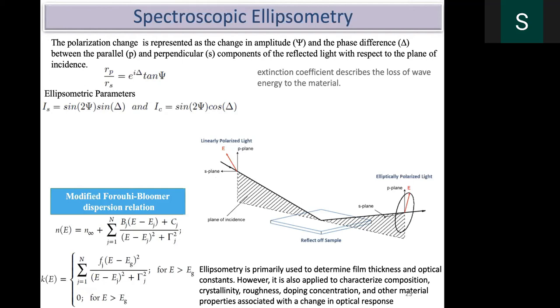Sometimes, if you have proper modeling, like we have used Forouhi-Bloomer, or some special model, you can find out the composition also from the system. For example, how much doping is there, you can indirectly get the details from this ellipsometry. It's a very versatile technique which is used in the semiconductor industry.